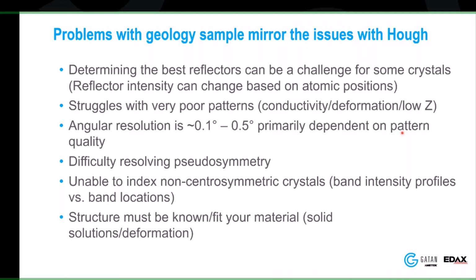It struggles with poor quality patterns. So the Hough has issues with these lower quality patterns. The things that cause those would be conductivity, low Z, or deformation. Those are three problems that we often have with geological samples. Well, most of them are conductive. Oftentimes, we're looking at them because they are deformed, and we tend to be low Z in general because we're silicates and other things like that.